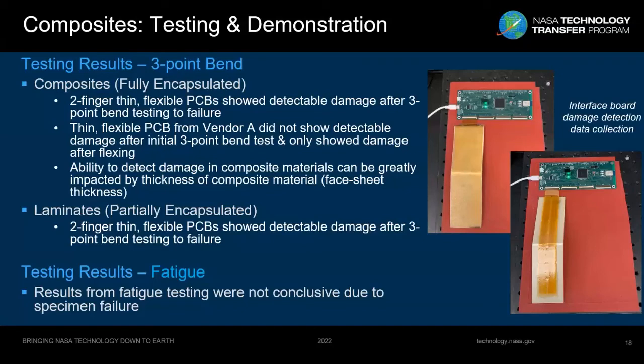These face sheets are pretty thin. And we know for sure that the thicker the face sheets, the more likely we are to see a bigger impact on our embedded flexible circuitry. And then on the laminated system, which is the one you see a little bit lower, you can see where the damage occurred. We are absolutely able to see the damage and the tearing, and we actually looked at these under a microscope, and you could see the physical tearing of the embedded circuitry there.